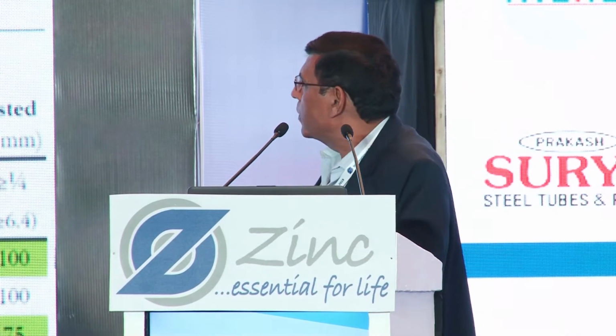And again, what I have told in the previous slide is confirmed from the fact, again Doug told very nicely, when you put a galvanized rebar into the concrete, the first fraction of microns reacts with the concrete and creates a very nice bonding. And that is the reason that the bond strength of this is very, very high. And this is a very positive thing which makes rebar useful for that.